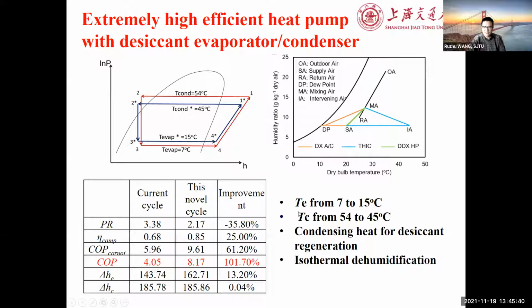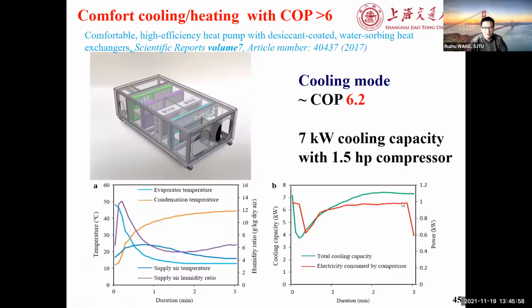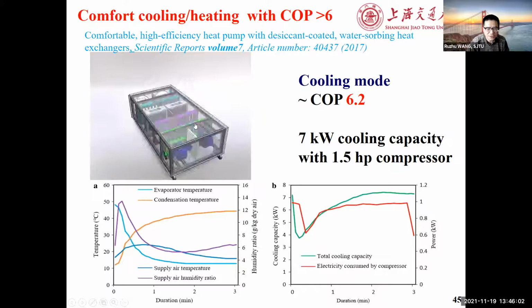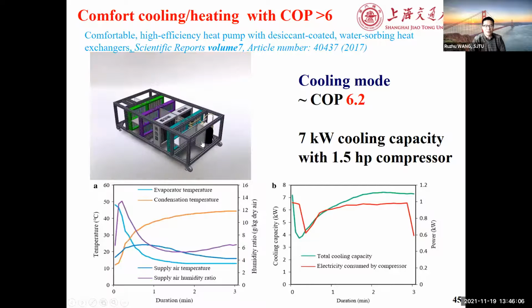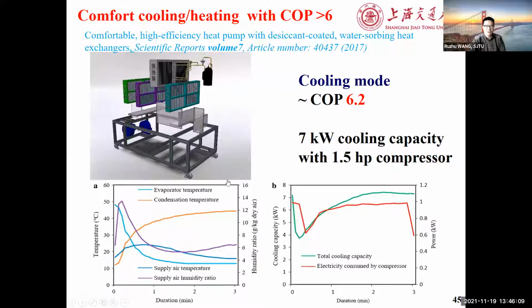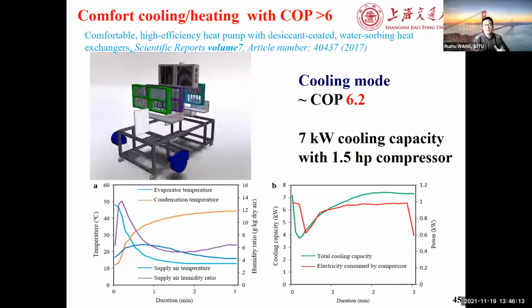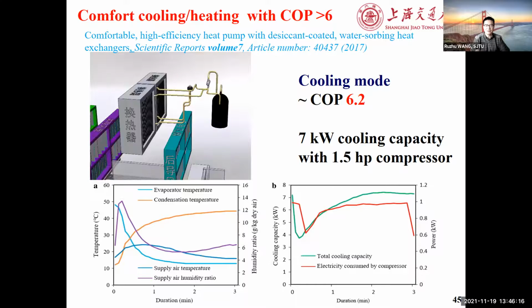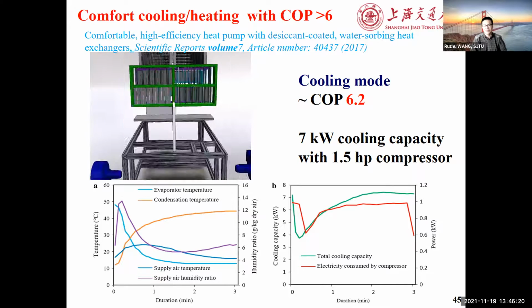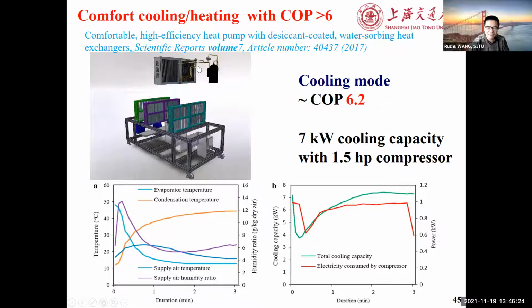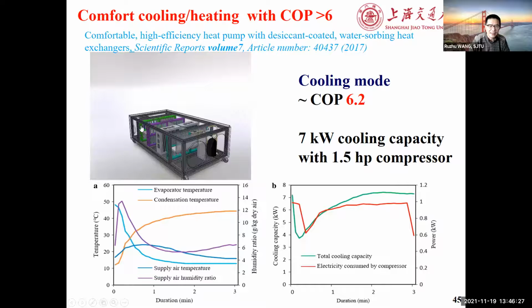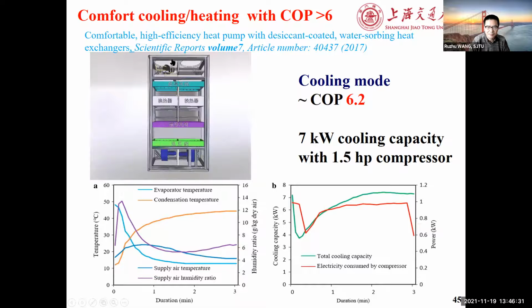So in this case, the COP value could be increased 100% theoretically, because normally more than 40% of the energy is used for the dehumidification. Now this just shows the air handling unit, and the system has only one compressor and two heat exchangers, but the evaporator and condenser need to shift phase. So maybe every 5 minutes you need to change the heat exchanger from evaporator to condenser. And also we have four-way valves here to make the shift of the phases of the heat exchanger, and also the air duct. You need to pump the air by the fan.